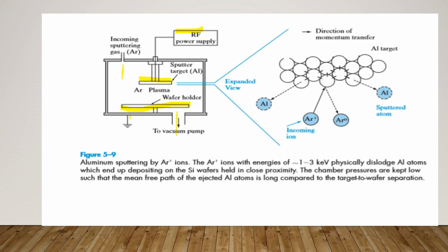The aluminium is then patterned using a metallization mask and subsequently etched by reactive ion etching. Finally, it is sintered at 450 degrees C for 30 minutes to form good electrical ohmic contacts on silicon, as well as to produce an alloy. After the interconnection metallization is complete, a protective overcoat of silicon nitride is deposited using plasma enhanced CVD. Then the individual integrated circuits can be separated by sawing or by scribing and breaking the wafer.